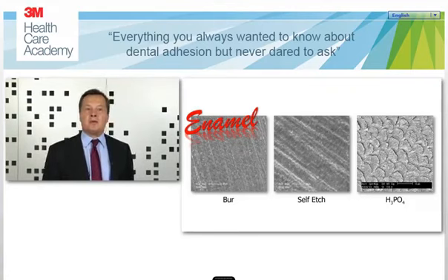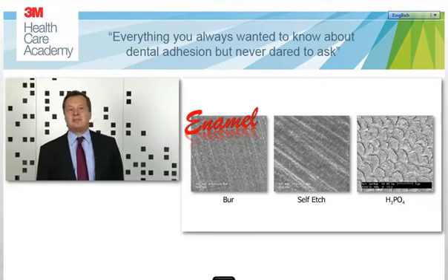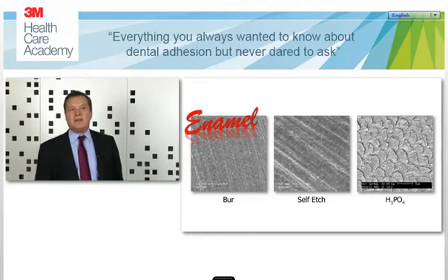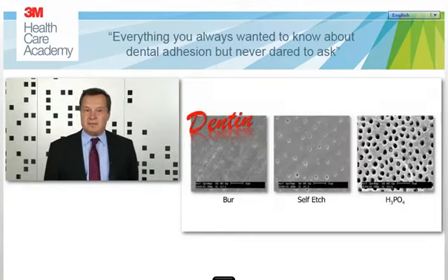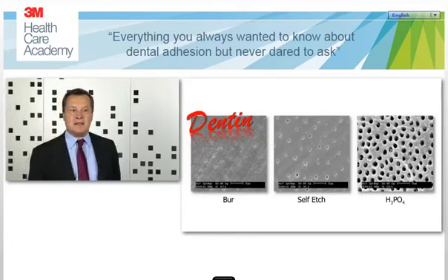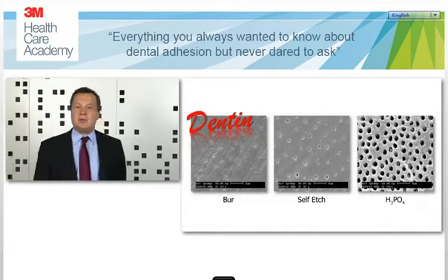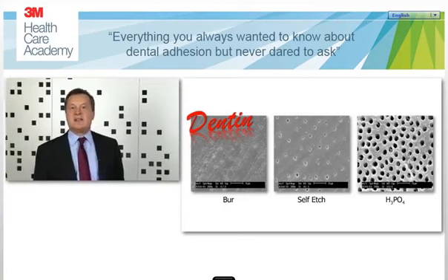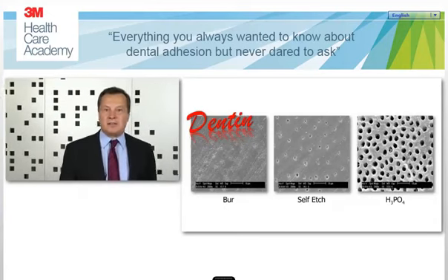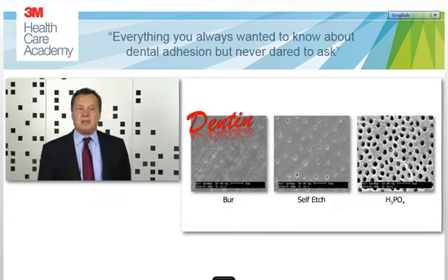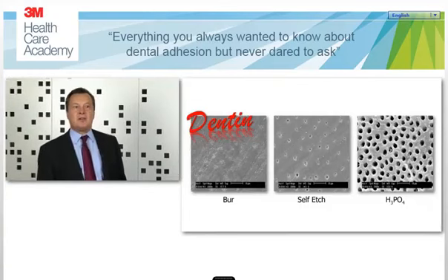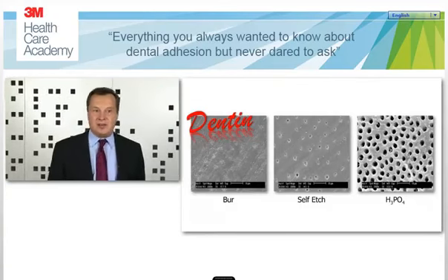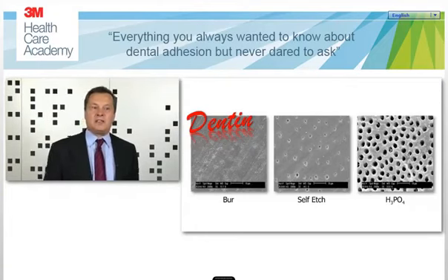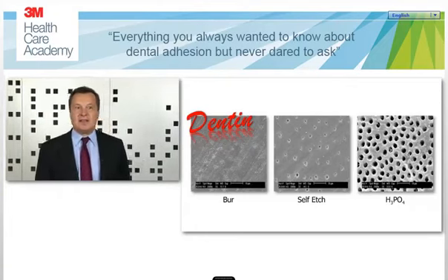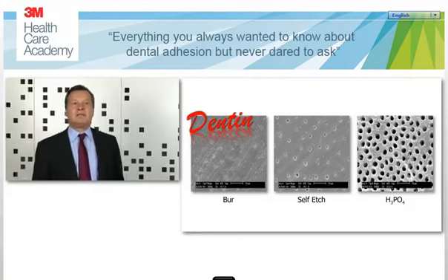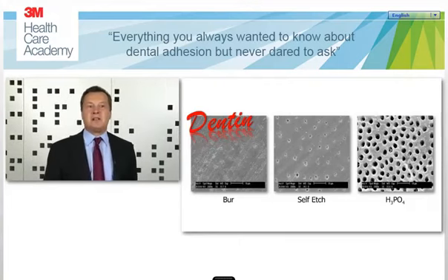And this is the reason why you can see this typical and nice etching pattern on enamel. This is also very similar on dentin. What you can see on the left-hand side of the slide is a burr-prepared dental surface. It resembles enamel a lot because, again, it is covered with a smear layer. By applying a self-etching primer, you can see that the smear layer is removed, but not completely removed. Especially you may see some remnants in the dental tubules in the middle of this slide. This is the picture which is shown in the middle.